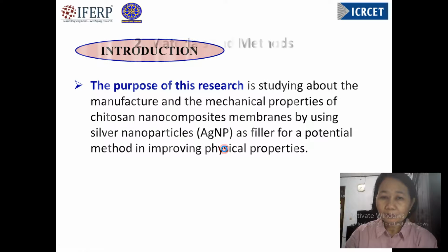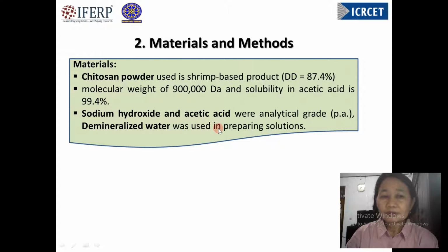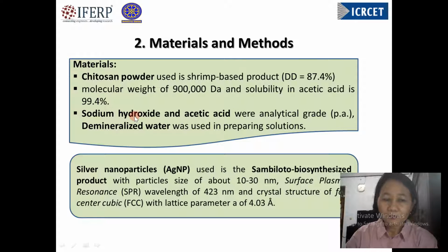as a potential method in improving physical properties. Material and method. Materials used in this research are chitosan powder, a shrimp-based product with a degree of deacetylation of 87.4%, molecular weight of 900 kilodalton, and solubility in acetic acid of 99.4%. Sodium hydroxide and acetic acid were analytical grade. Demineralized water was used in preparing solutions. Silver nanoparticle used is the Sambiloto biosynthesized product with particle size about 10 to 30 nanometer, surface plasmon resonance wavelength of 423 nanometer, and crystal structure of FCC with lattice parameter of 4.03 angstrom.